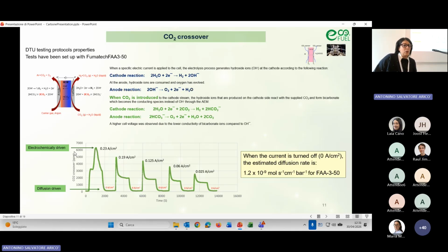So it was measured what is the contribution that we call electrochemically driven, of the CO2 that migrates, that is pumped to the other side when we apply a current, or when the current is zero. This is only the diffusion, so physical crossover. So in this graph, this is reported for the benchmark. We can see that the electrochemically driven crossover obviously depends on the current applied. And in the cell there are two CO2 sensors to measure the actual amount of CO2, and the diffusion driven can be estimated as 10 to minus 9 for the Fumatech membrane.